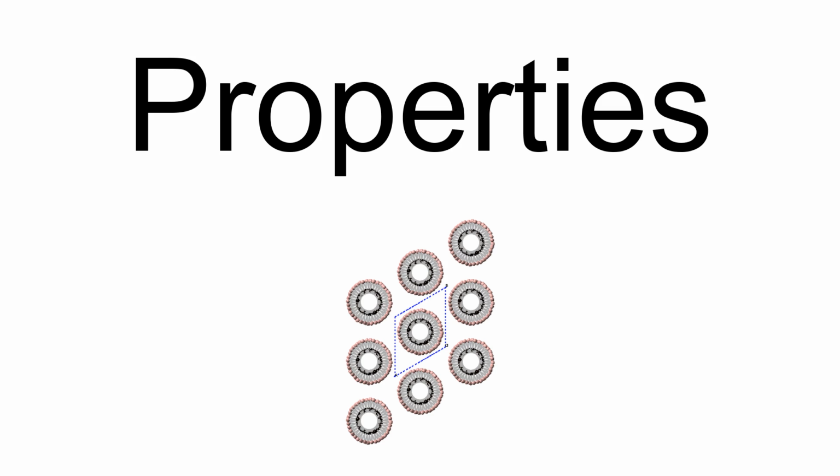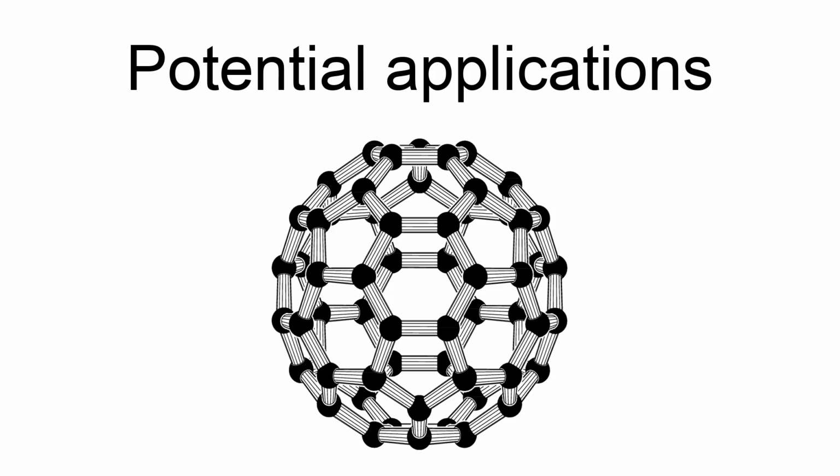Chemically substituted nanothreads may facilitate load transfer between neighbors through covalent bonding to transfer their mechanical strength to a surrounding matrix. Modeling also suggests that the kinks associated with Stone-Wales transformations in nanothreads may facilitate interfacial load transfer to a surrounding matrix, making them useful for high-strength composites.